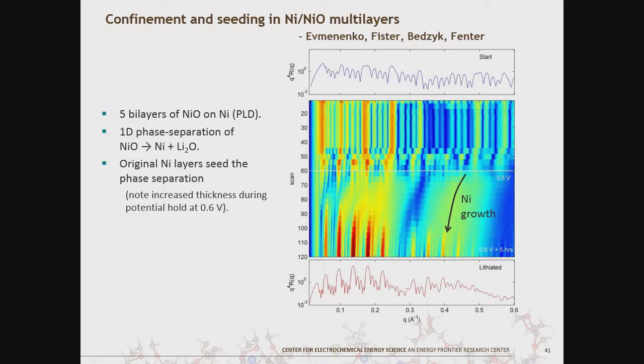As we drop the potential down, at this point we're at 0.6 volts, which is the classic voltage where things happen. There are slight changes before that, but around 0.6 volts we held it at this point. You can see the multilayer disappears because the layers get jumbled, so you no longer have regular spacing. But you still get these lobes of intensity, which are the form factors of the individual layers. You can see those lobes get small and move to smaller angle, meaning they're getting thicker.